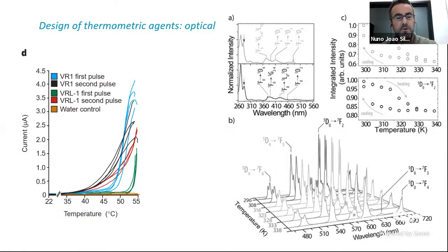If you remember what I just showed you a couple of slides before. You don't have a well-defined relation between temperature and this physical property. In that case it is current, in our case it is fluorescence intensity, but you don't have this well-defined relation, and you have hysteresis. So we have here something which is more complex, and it's not a good thermometer in the sense that we can have a value which is unequivocally related to the present temperature, but we have something that has some sort of a memory that we went to a higher temperature, and then slowly it starts forgetting this memory. So it's something more complex, but also more interesting if we are able to extract information from that.